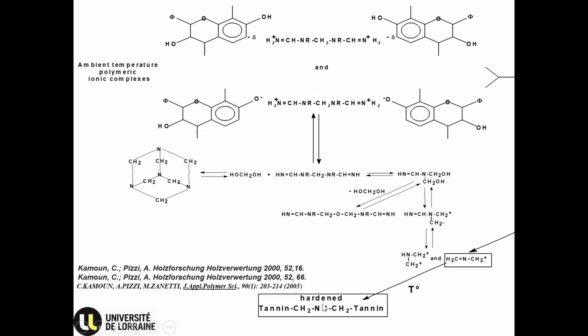And it forms a bridge of this type with the tannin that is stable, and the NH that is free contributes to absorb the formaldehyde that is emitted by the wood heated itself. So the emission is 0.0, effectively checked.